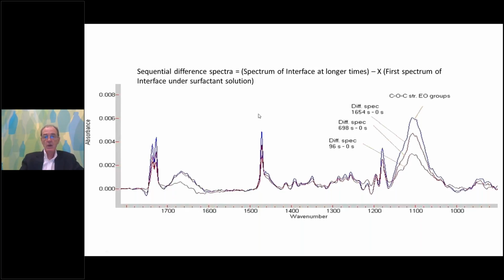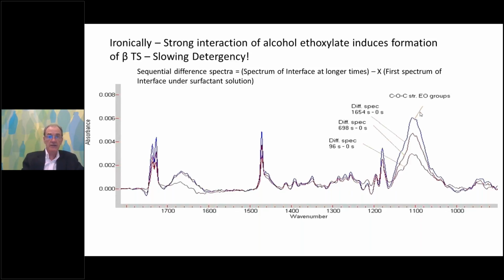What we see instead is that over time, bands due to beta tristearin grow and increase in intensity. In addition, we see the increase in COC bands due to the non-ionic surfactant adsorbing at the interface. So ironically, that strong interaction of the alcohol ethoxylate, while it's solubilizing some of the alpha form of the tristearin, actually penetrates into the crystal structure, and you can think of it as a partial loosening or liquefaction of the methylene chains of the alpha phase, and that accelerates the annealing so that the chains can reorient into their thermodynamically favored state, which would be the beta phase, which is much higher melting and ultimately not easy to remove.